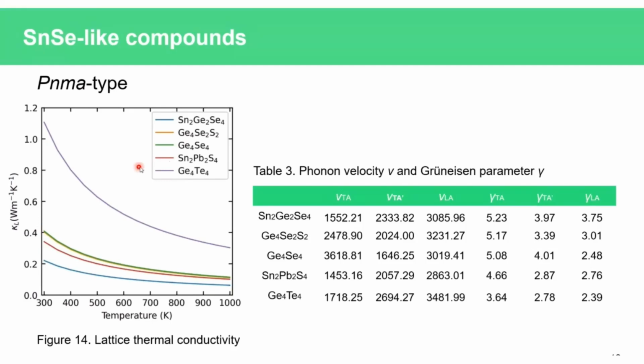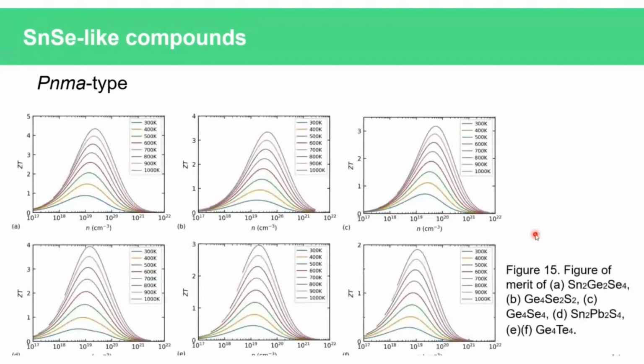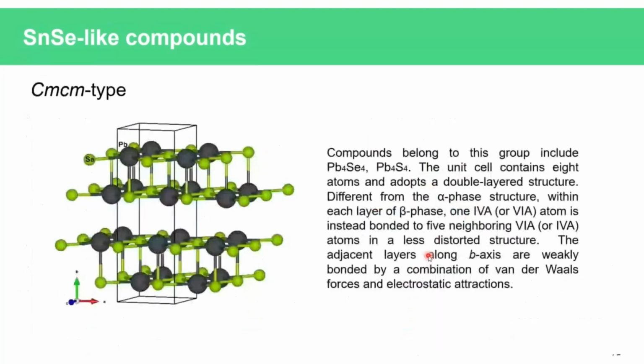So we also calculated the phonon velocity and analyzed the phonon velocity and the Grüneisen parameter. Such a low lattice thermal conductivity mainly comes from its large Grüneisen parameter, which indicates the strong anharmonicity intrinsically in the lattice. Due to such a low lattice thermal conductivity, their figure of merit value can be higher than 1 in a wide range of temperatures and carrier concentrations.